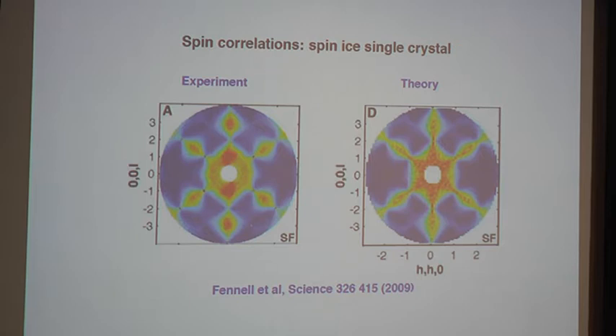then there are single crystal diffraction experiments, and when, instead of averaging over orientations, you look at diffraction resolved by angle as well as magnitude of the wave vector, you find that there's lots of sharp structure in reciprocal space. So although you don't have Bragg peaks, you do have structure which is sharp, and in fact in pretty good correspondence with theories which I'll talk about.